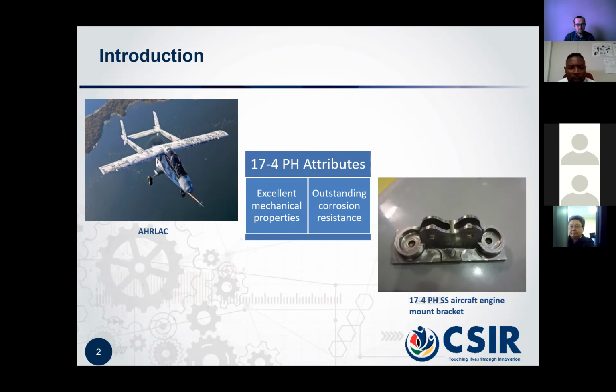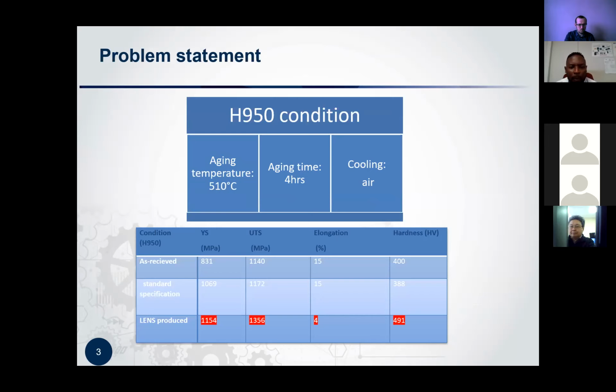And this component, as I said, is made out of 17-4 PH stainless steel, and they choose this type of material because it's suitable for the application. It has excellent mechanical properties and outstanding corrosion resistance. Now the problem came when we did process development. We did find our optimum process parameters for the LENS. We were able to produce something which was dense. And then the problem came when we applied the post-processing, which is the H950 condition. That bracket is in an H950 condition.